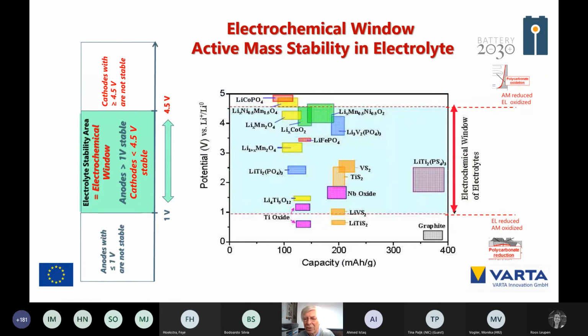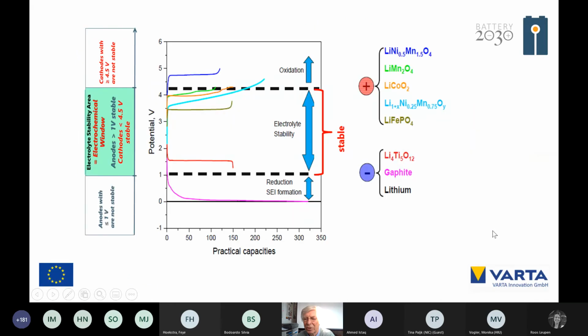So that is what we have seen here. And in that case, the electrolyte is reduced and the active mass is oxidized. So that is in general. And you could see that here. Again, that electrochemical stability window, and the lithium nickel manganese oxide is outside, and also the nickel manganese oxide of different composition is coming up at about, let's say, 50% charge. We are coming also into the instability area.